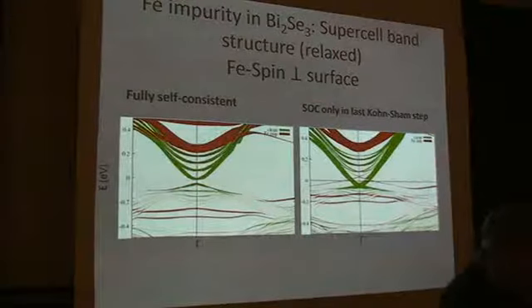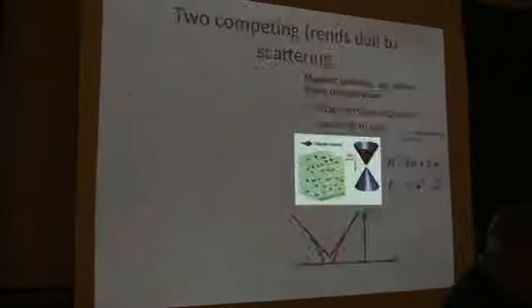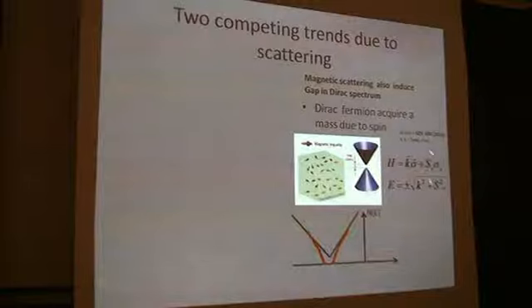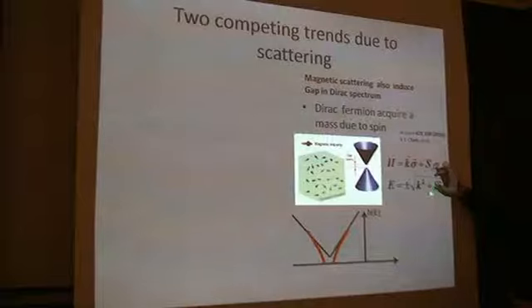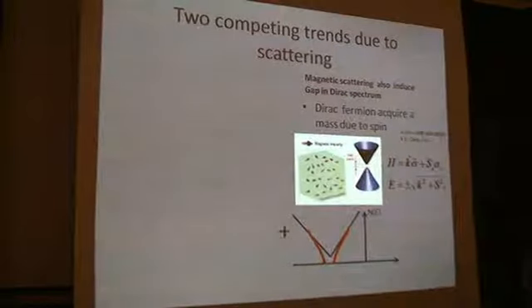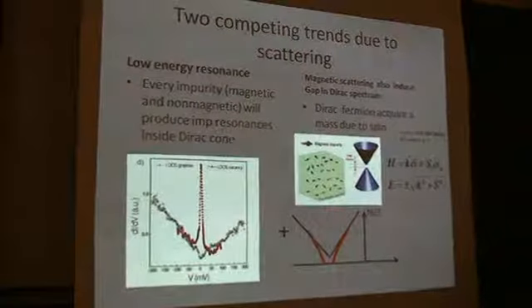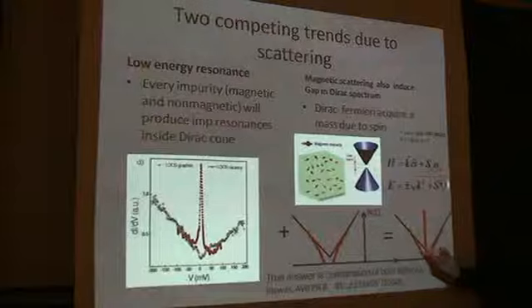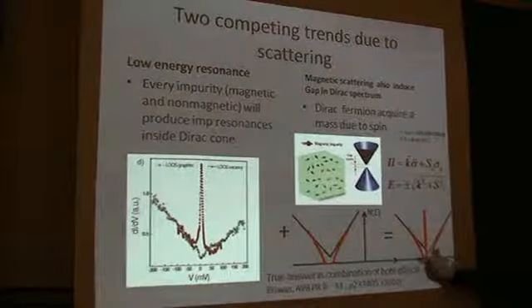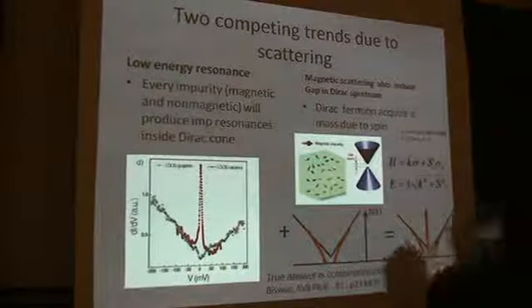But I would say that the way it appears to me, when you look at the discussion of the effects of magnetic impurities, is that people often use this very simplified Hamiltonian where I look at the Dirac Hamiltonian, and I have essentially a homogeneous, non-scattering external field produced by the spin polarization. What this calculation forgets to note is that any of these impurities also come with local scattering potentials, which are non-magnetic. You cannot bring a magnetic impurity into a crystal without having some scattering induced as well. And so I think it's certainly true that this term itself will open up the gap, but in addition, my working hypothesis would be that there will be some intragap resonances. So the net effect is that if we have all the spins lining up out of the plane, or an applied magnetic field, we do have a gap opening, but there will be some, call it intragap states inside, that are induced by scattering.